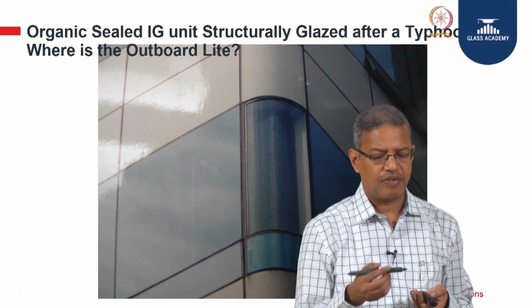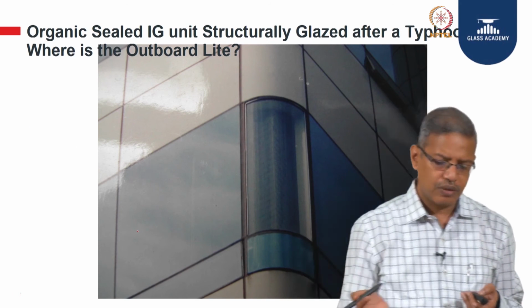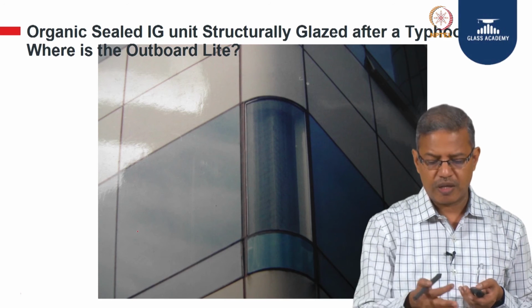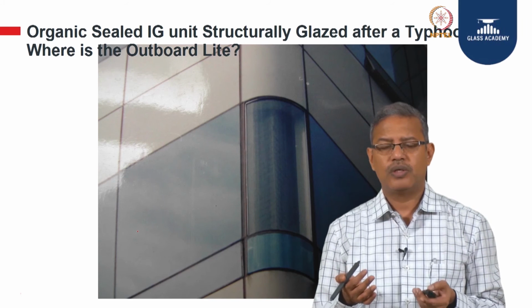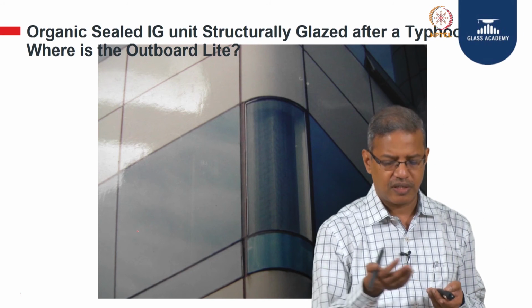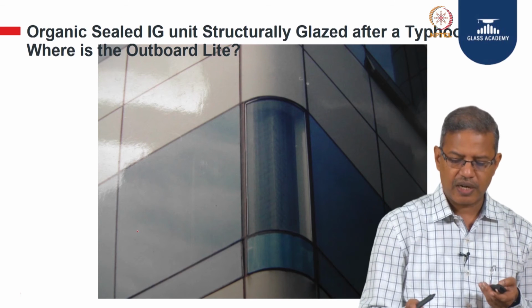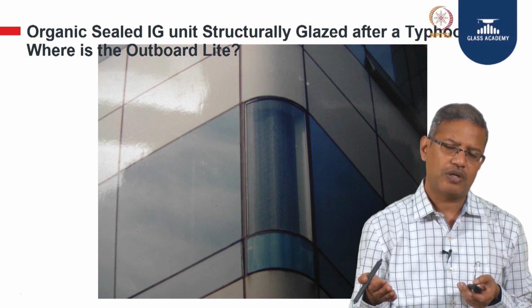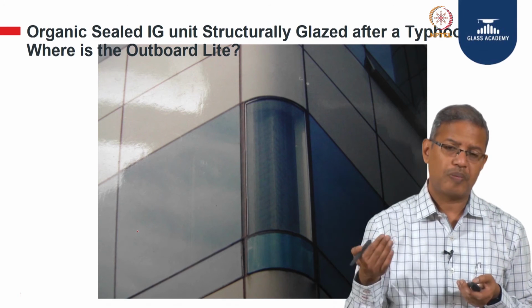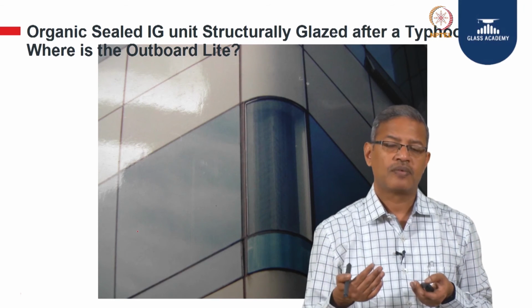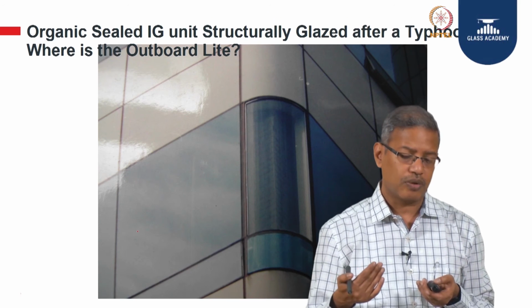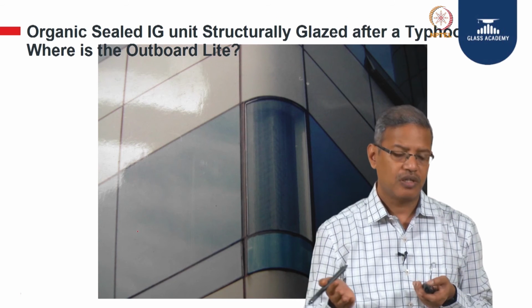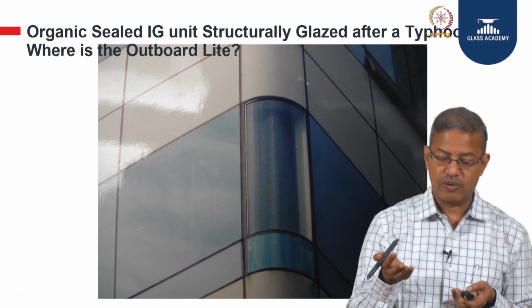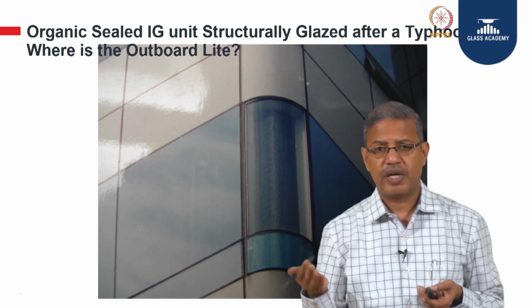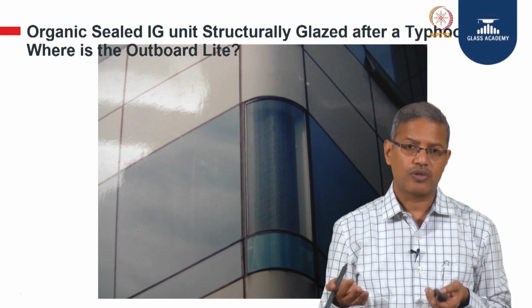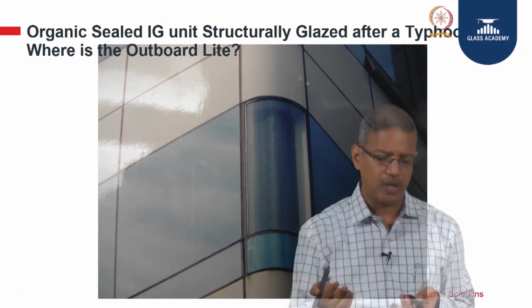This is one of the projects wherein there was a typhoon and corner glasses were replaced, and somebody had replaced them with a double glazed unit made with an organic sealant. After the typhoon, only the inner glass and the spacer remained, because the inner glass was structurally bonded to the system using silicone sealant. The outer pane, which was the DG made with organic sealant, had fallen out. I have seen this personally in my experience on some of the complaints, and I could really see how these sealants behave when exposed to climatic conditions like what we have, and also to the loads and stresses they are subjected to, and to water.